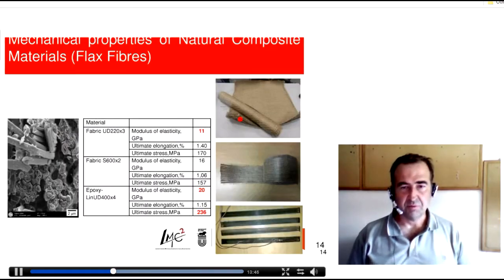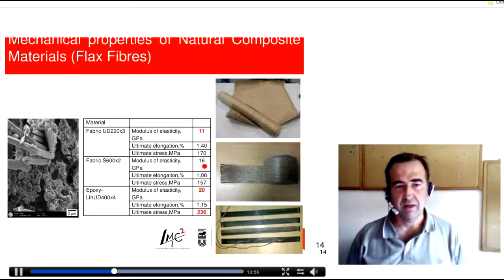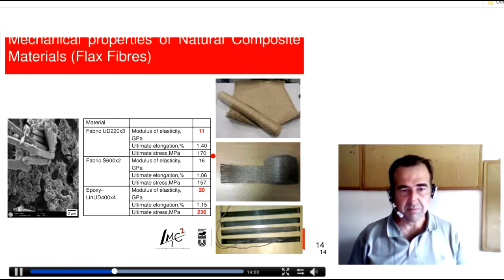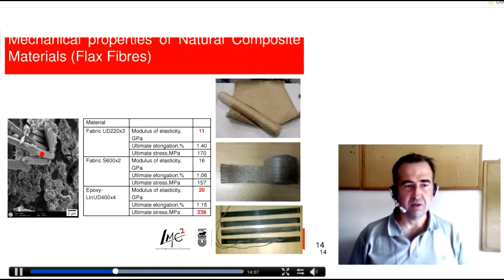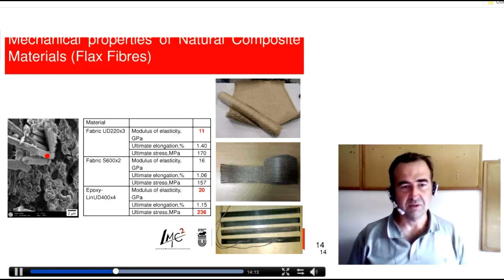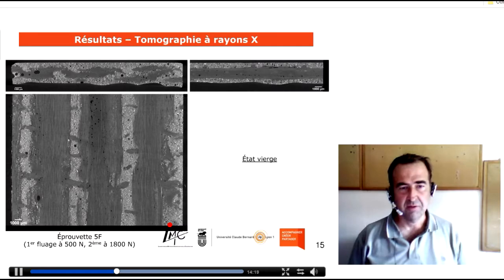This is some photos of how the fibers look, and what we get at the end is a Young modulus of about 11 gigapascal and a tensile strength of about 170 megapascal. You observe here that some debonding of those fibers may occur, and this obliges us to use two epoxy systems, one with a high viscosity and one with a low viscosity, allowing to bond this onto concrete.